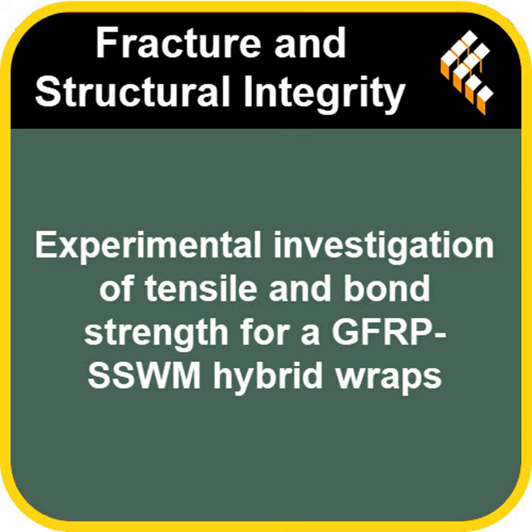Pure GFRP often doesn't deliver its full strength because of debonding. But the hybrids, especially with the right epoxy, get much closer to their potential. Almost 90% utilization, which is excellent. And finally, that counterintuitive point about layers. Two-layer hybrids often perform better overall, balancing strength and ductility compared to three layers. More isn't always more. Sometimes optimization is key.